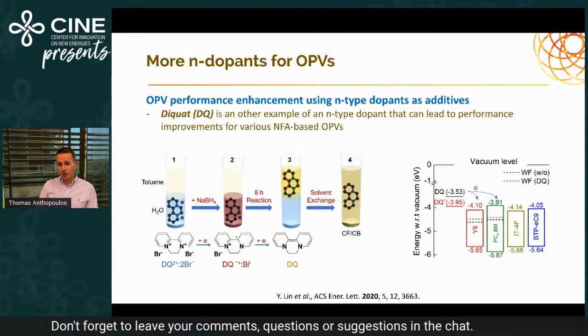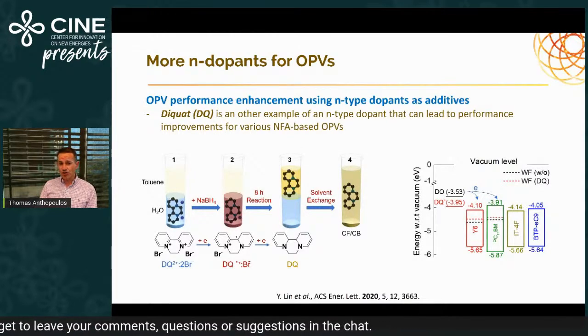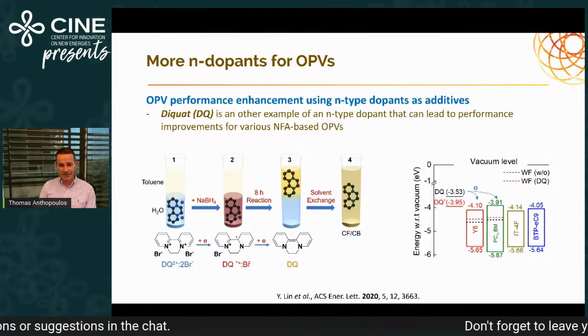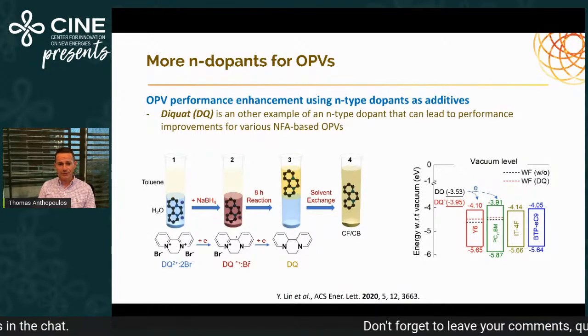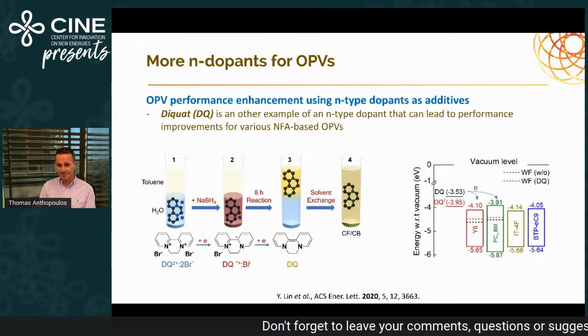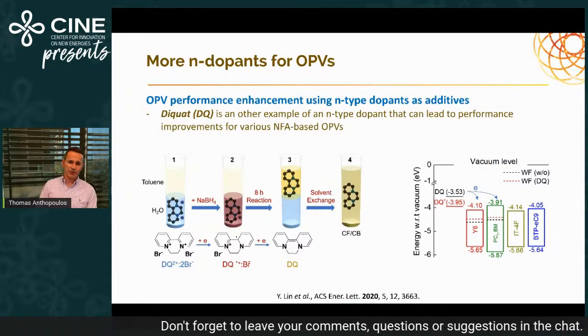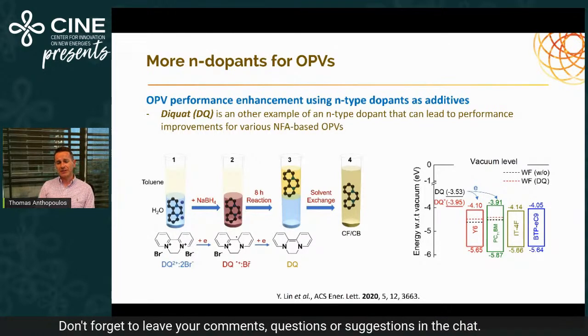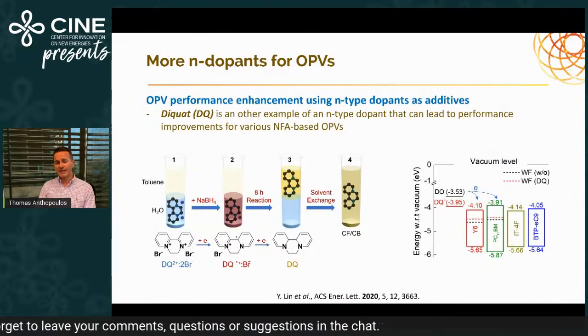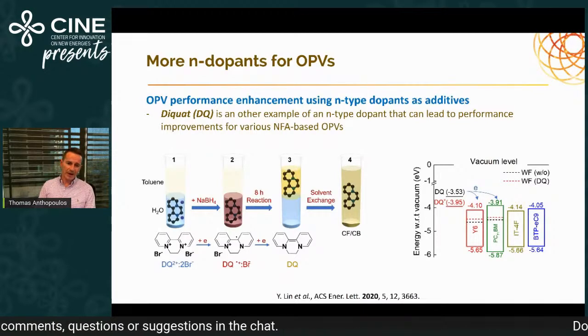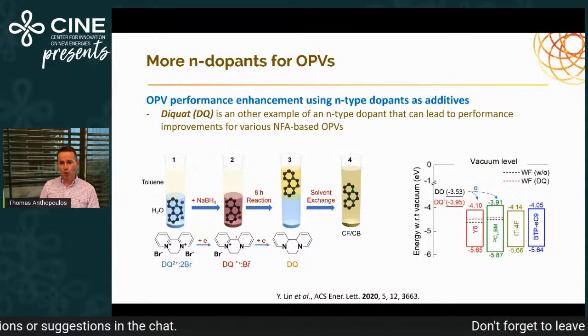Another example, which we discovered a few years later, was essentially the Diquat (DQ). This is a commercially available material. It comes in a salt form. You have to separate the neutral Diquat (DQ), add it in your bulk heterojunction, and we saw essentially this Diquat (DQ) playing a major role as a microstructure modifier, as well as a moderate dopant.